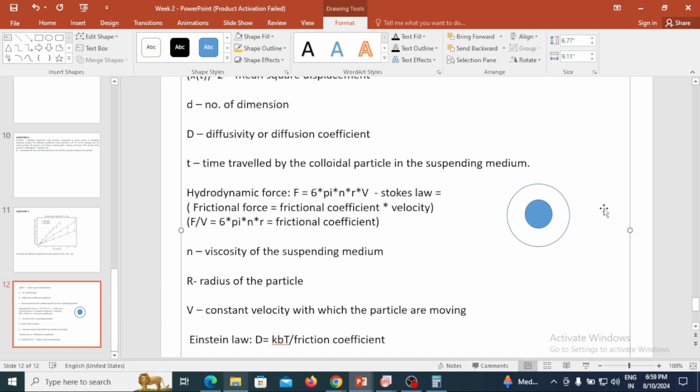If you calculate the size of a particle through DLS and through a high resolution microscopic image like a scanning electron microscope, there will be a difference of approximately 30 to 50 nanometers, and that difference is due to the liquid molecules that surround the surface of the particle. Since these molecules surround the radius, the radius that you obtain through DLS is called the hydrodynamic size of a particle and not the size of your particle as such.